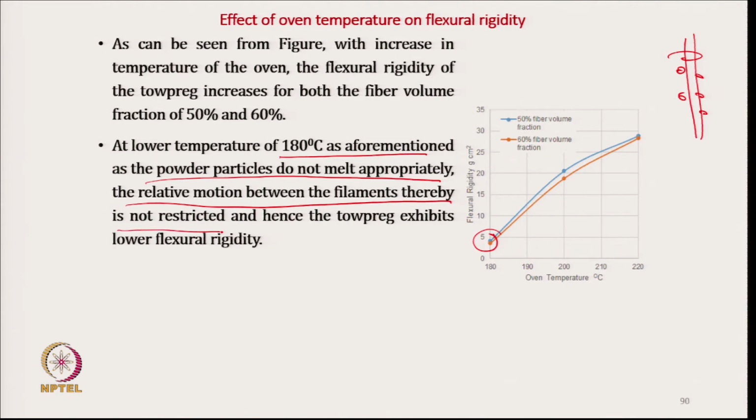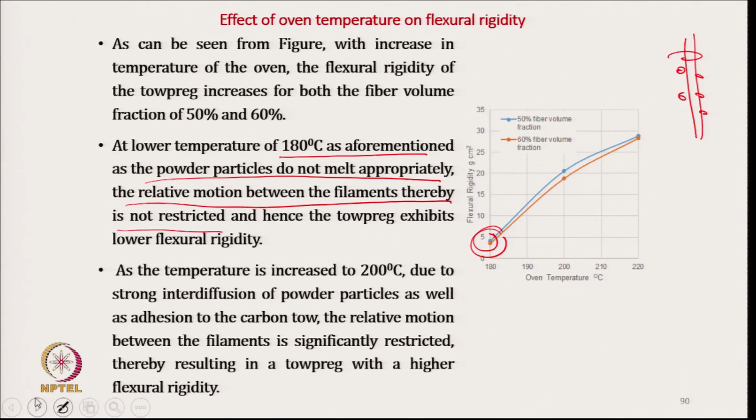So, towpreg exhibits lower flexural rigidity, but at higher temperature these particles get melted, covered, as we have seen in the scanning electron microscope photograph, and due to this the bending rigidity, flexural rigidity increases.